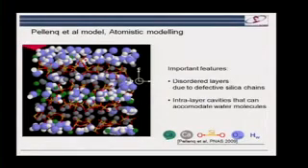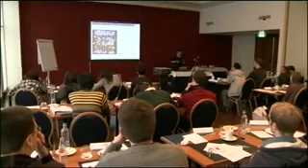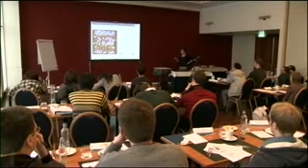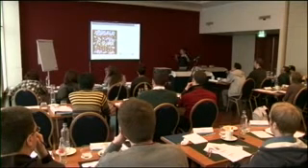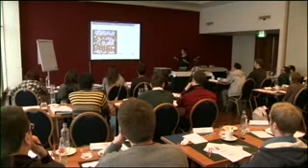And this is a model that was published recently in PNAS, where they tried to put in the different distributions of silicate chains and come up with a model for what they call CSH. There's a lot of controversy about whether this is right, or whether they have chosen the right distribution. That's an ongoing debate, but the important point is that as you start to remove these silicates, these layers become disorganized.